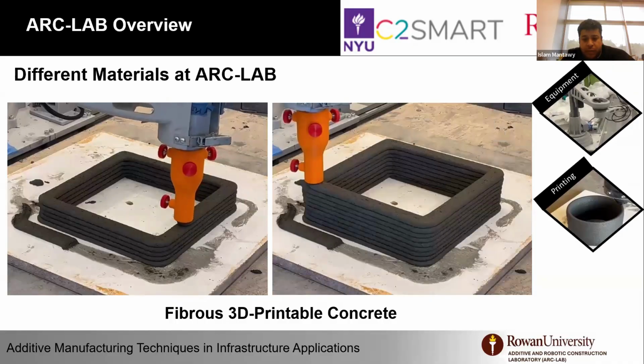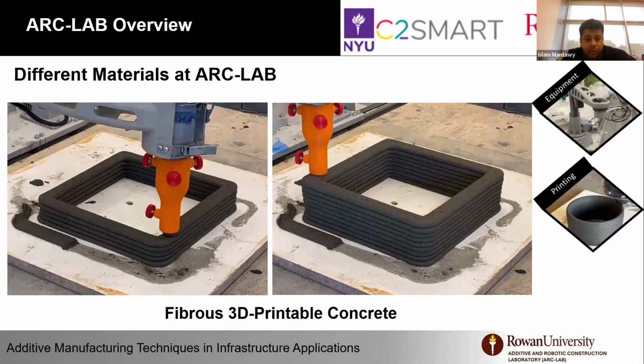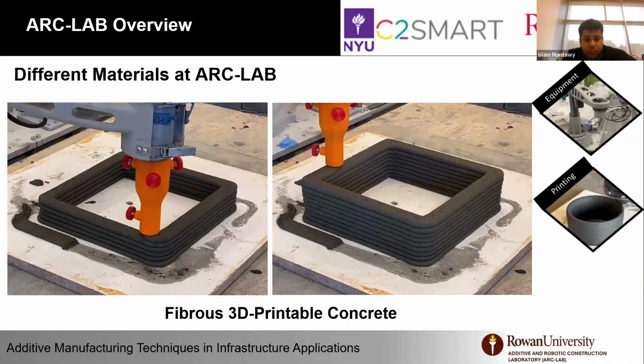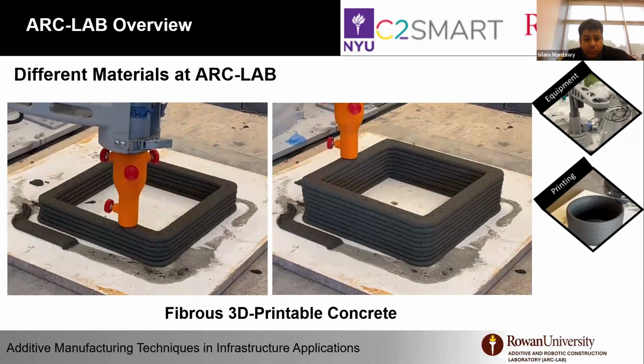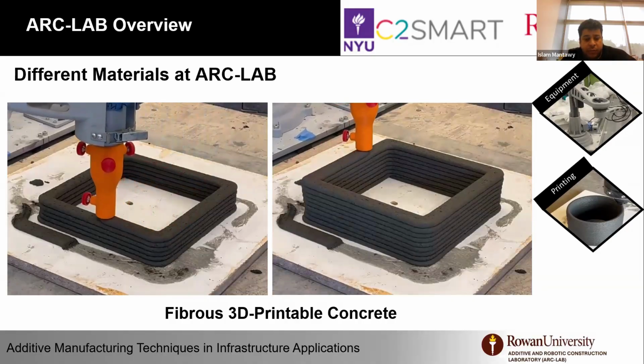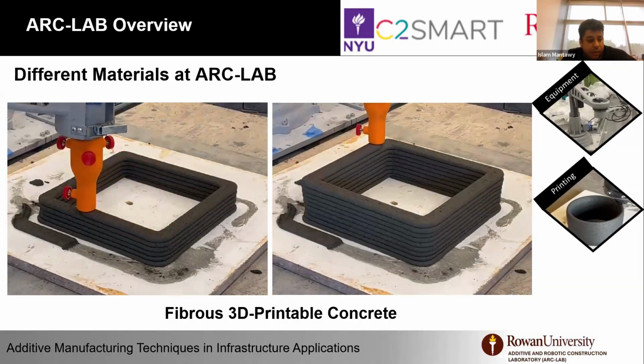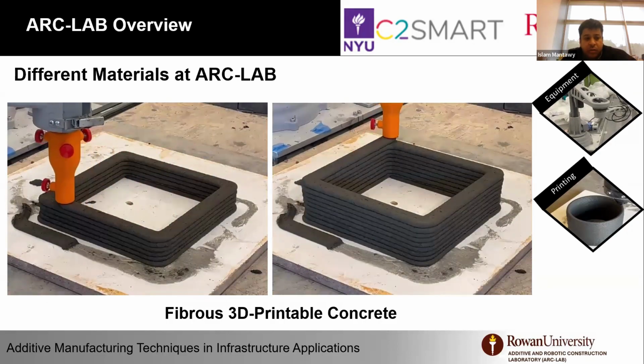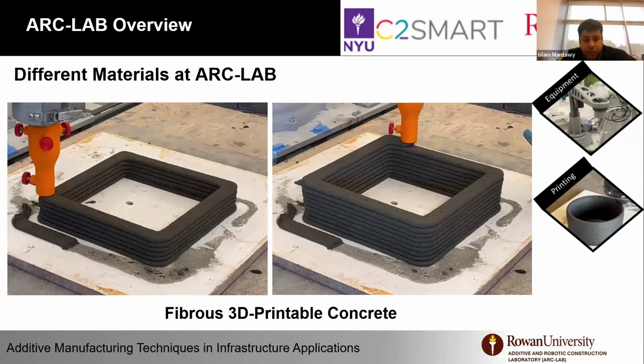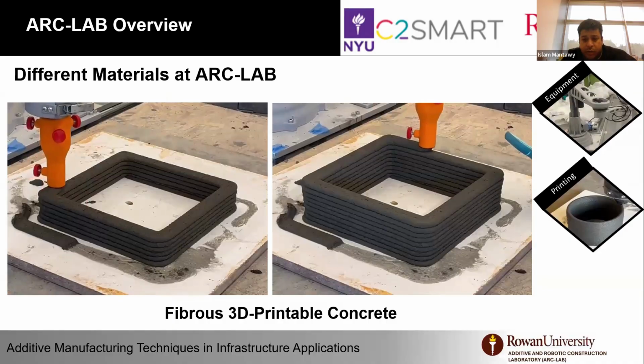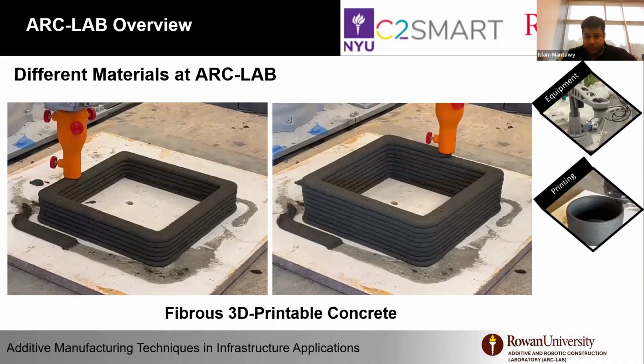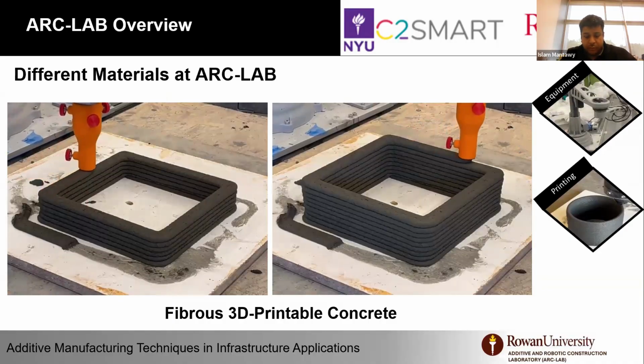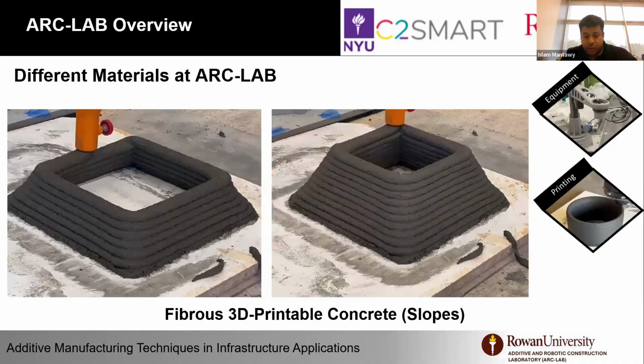We also have mixes that we formulated using fibers. The mixes include steel fibers. We examined 4.5 millimeter, 6 millimeter, and 12.7 millimeter fibers within the mix and extruded within the matrix. So you can see here, we also have various mixes that are actually printable with steel fibers.